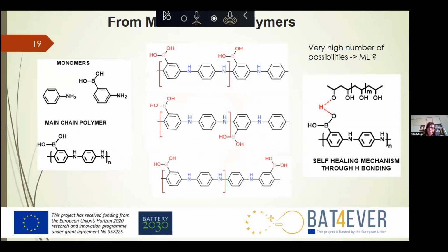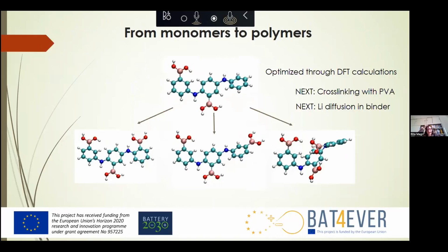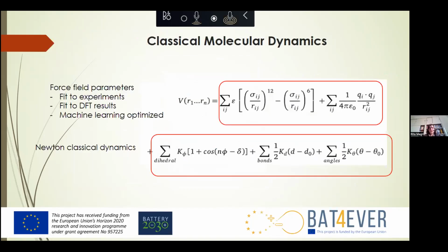Then we want to go from monomers to polymers. So we have implemented all these results in building larger structures. We are now implementing the multi-scale approach in which we start from monomers and optimize them, and then polymers, and then we also want to proceed cross-linking them with PVA and then study diffusion in the binder. A few words and then I close on classical molecular dynamics.